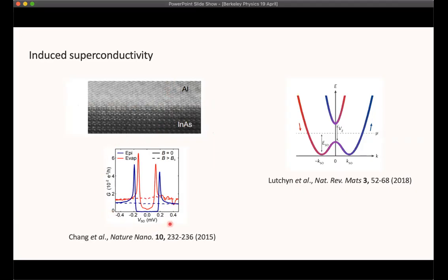And so in this plot here of tunneling spectroscopy, which I'll describe a bit more later, we see a superconducting gap. So that's the space between these peaks in conductance. And this is a gap in the indium arsenide. This is telling you the indium arsenide is in fact superconducting. The quality of that gap, both the size and the depth, depends on how the aluminum was laid down, whether through epitaxial growth or through evaporative deposition. So this is the kind of measurement that we do to check on the quality of our materials interfaces.